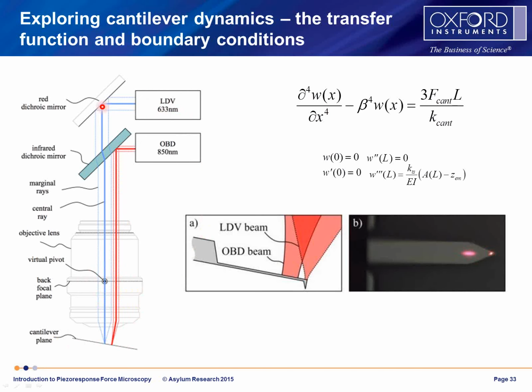The interferometer is independent. It can be steered around and positioned in this plane or this plane of the sample or anything else independently. This photo shows the optical beam. It's a larger spot, and then the interferometer beam is a tiny spot. And this is an actual photograph with one of the cantilevers we actually use for PFM. So you can see the optical beam is here, that runs an AFM as it normally would. And then this little spot here can actually go along and measure